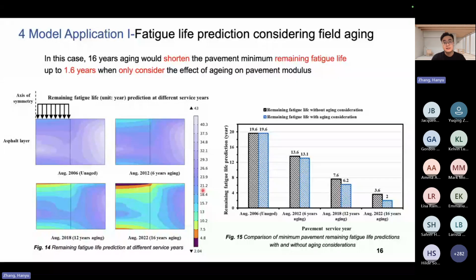Now we understand that aging has a substantial effect on pavement performance, but we still need a quantitative indicator to show the aging effects. The figure on the left shows the remaining fatigue life predictions at different aging years. The right figure shows the comparison of the minimum remaining fatigue life predictions with and without aging considerations. In this case, 16 years of aging would shorten the pavement remaining fatigue life by up to 1.6 years when we only consider the effects of aging on pavement modulus change and the modulus gradient.